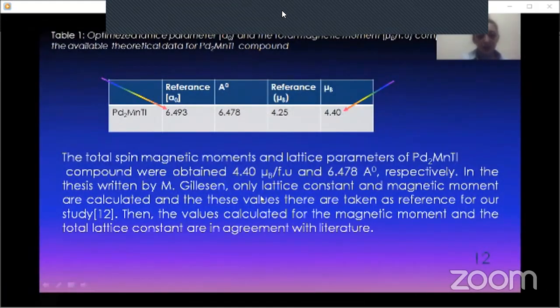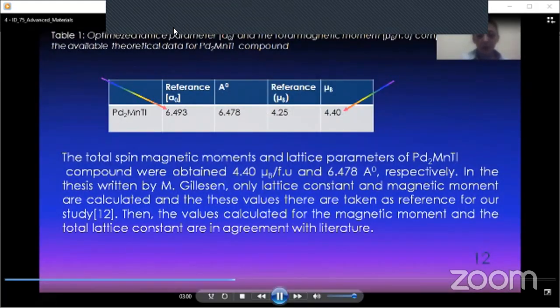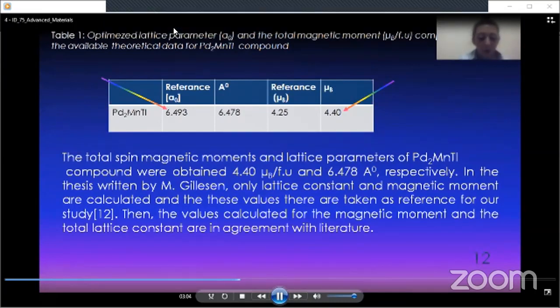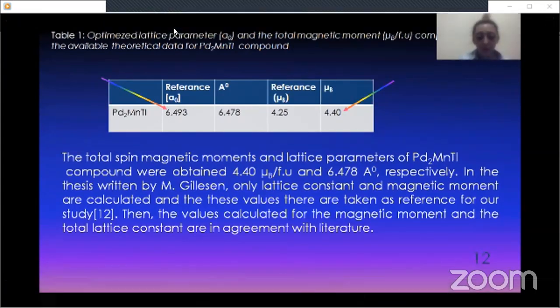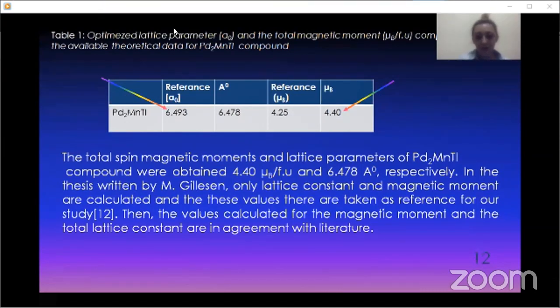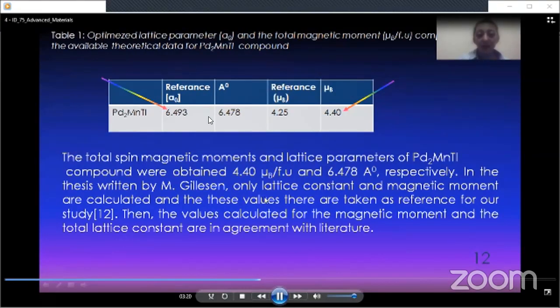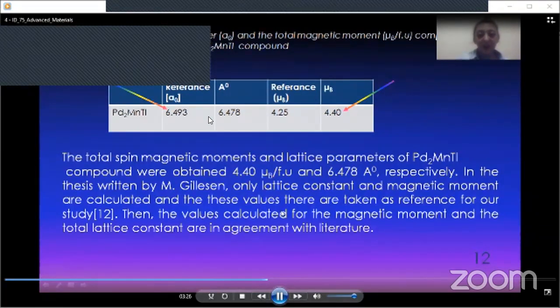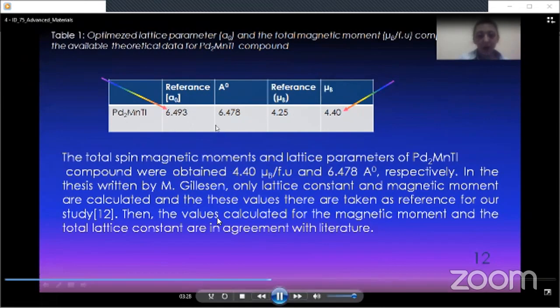The total magnetic moment and lattice parameter of the palladium manganese thallium compound were obtained as 4.40 Bohr magneton per formula unit and 6.478 angstrom respectively. In these cases, all the lattice constants and magnetic moment were calculated and these values are taken as reference for our study. Then the values calculated for the magnetic moment and the lattice constants are in agreement with the literature.